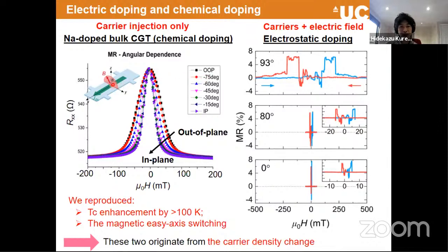What I'm trying to say is that when you switch in plane, we don't see any magnetoresistance of this size. But if you remember, the size of the magnetoresistance is very different when you switch out of plane, up and down, and also in plane, on the order of a factor of 50%. So clearly that's something we can tell by looking at the two different results, and we are really working on this point.